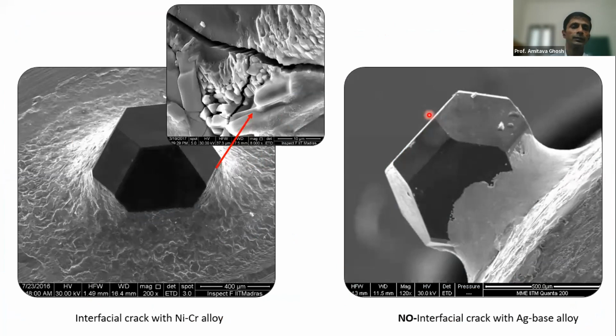So we thought about how to tackle this problem metallurgically, first of all. And metallurgically, as I said, the root cause is the residual stress. We thought, why not use a filler alloy which is much softer, in the sense it is much more ductile in nature, and with adequate Young modulus, which means basically it will absorb. It is more tough. We need it tougher, but at the same time it should be able to absorb. It should show more ductility. That means the strain at fracture should be much higher than the nickel chromium alloy.